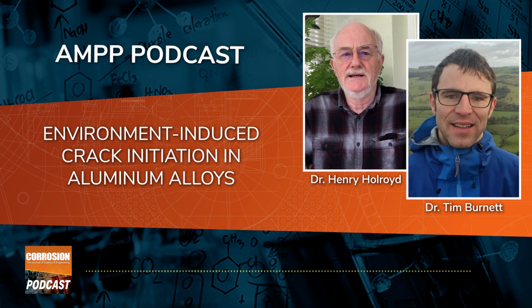And then you could look to surface treatments and things like that, which specifically are trying to counteract that mechanism. I think one of the real challenges that still remains, as well as needing to just do a lot more work on initiation in general, is that when you consider an in-service scenario, the diversity of the environment is often really difficult to track, especially when you think about aircraft and things in ambient environment where the temperature can change drastically, or the humidity, or it can get wet and dry. All of these things make it very, very difficult to see what effect long-term that will have on initiation, what effect long-term that will have on propagation.